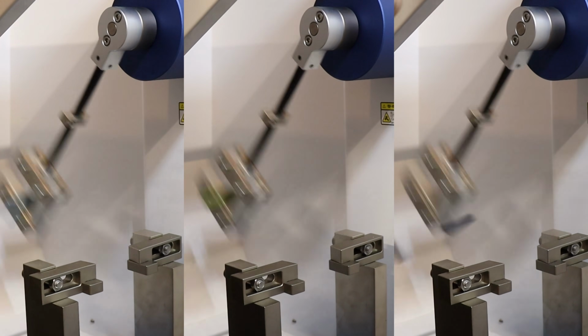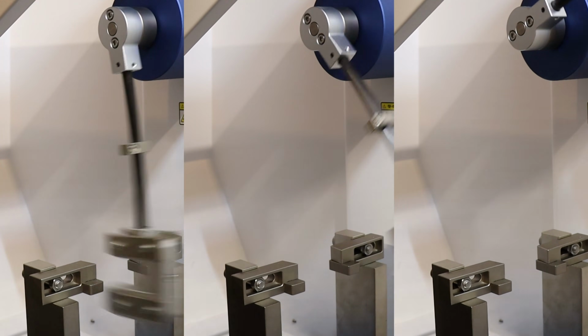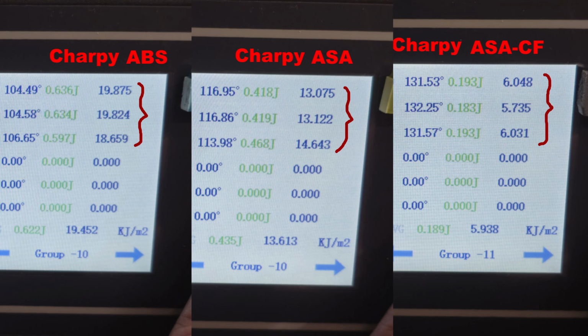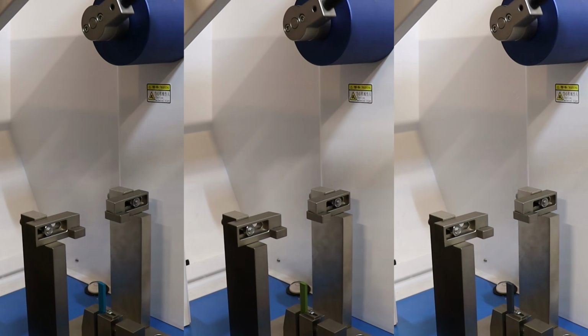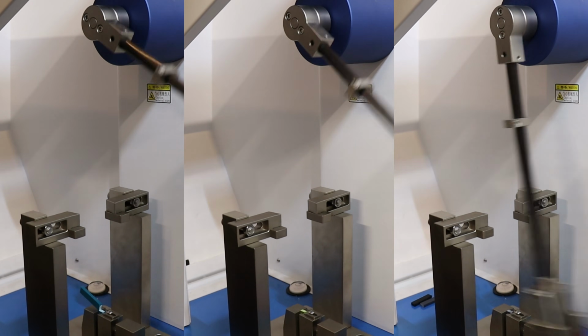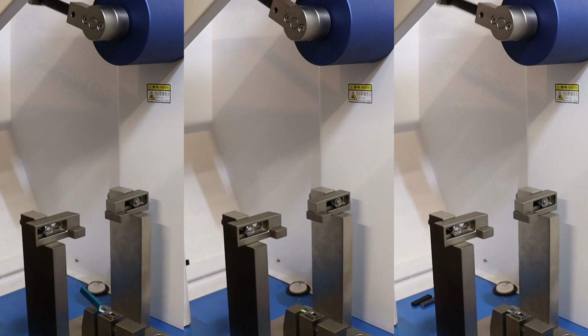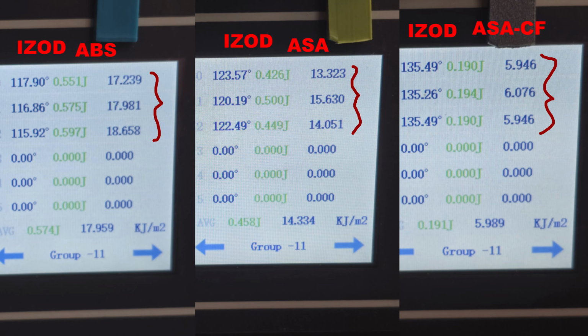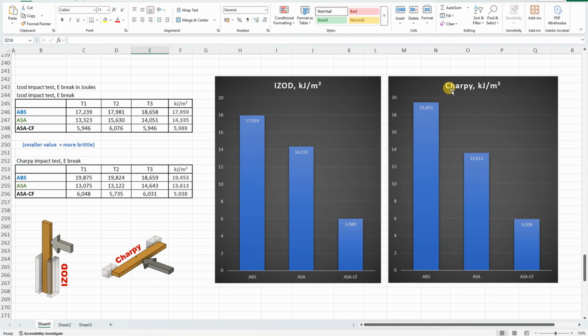Charpy impact test, supported from two sides. All results side by side. IZOD impact test, hold it vertically. And results for the IZOD test. These are two different types of the test, but very similar ratio we can see here. The toughest is the ABS, as this is very important advantage of this material. The second is ASA, and the most brittle between these three is ASA-CF, but even this is tougher than average